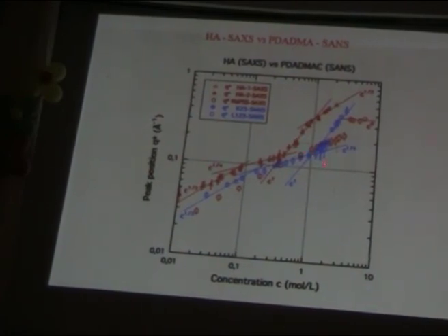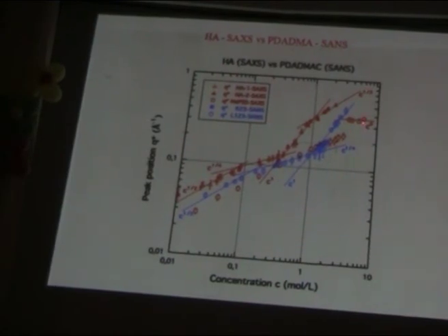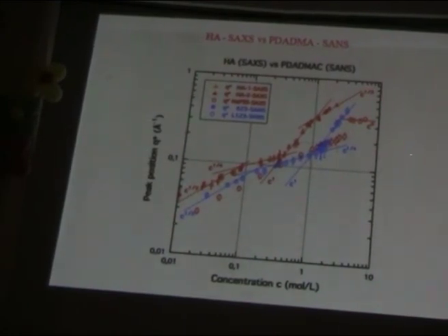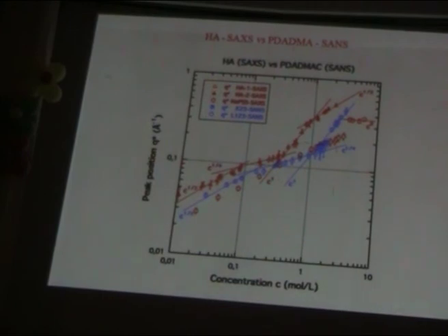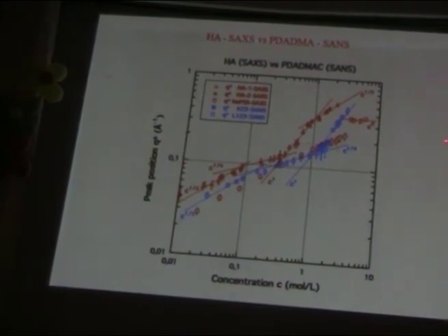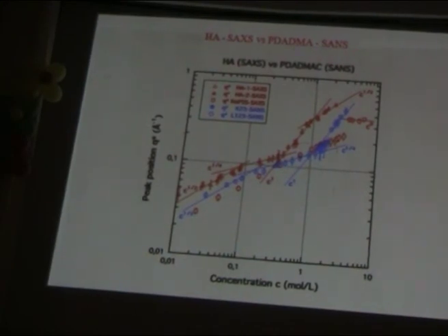When you compare that, you see, of course, first, that the jam regime appears when you obtain the Q star close to the persistence length. But you also observe the difference in the naked persistence length, the non-electrostatic persistence length, of the two polymers. That's all. I'm sorry.